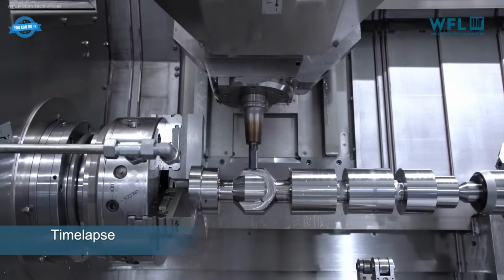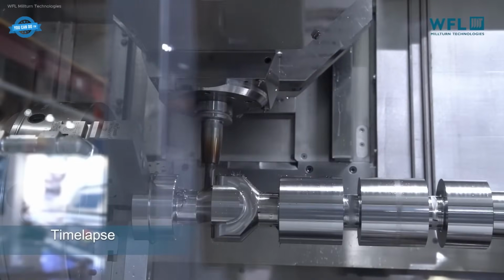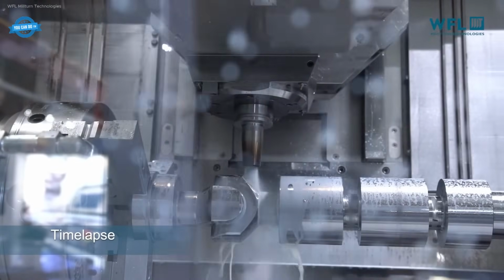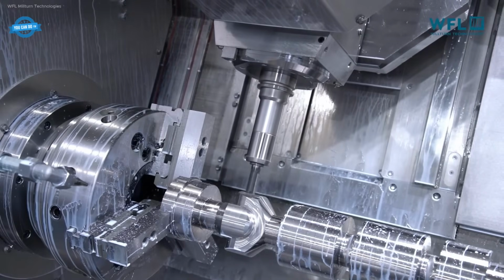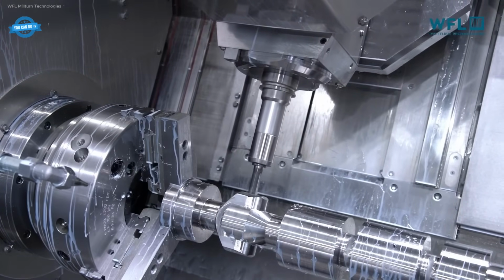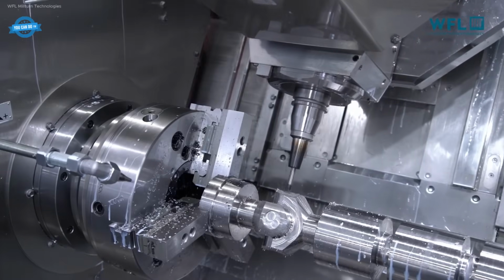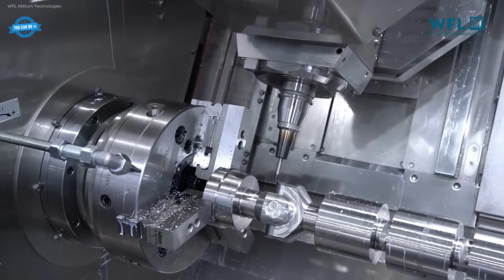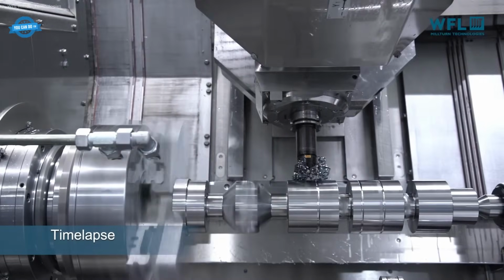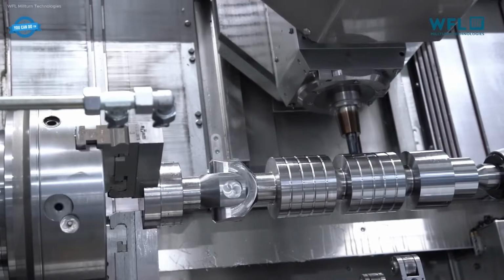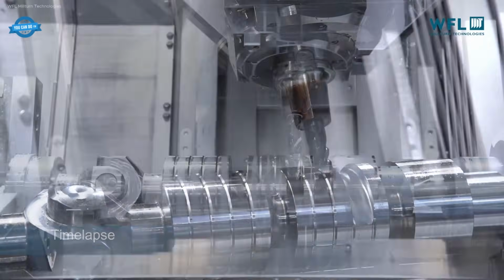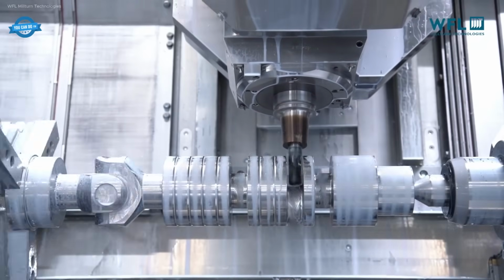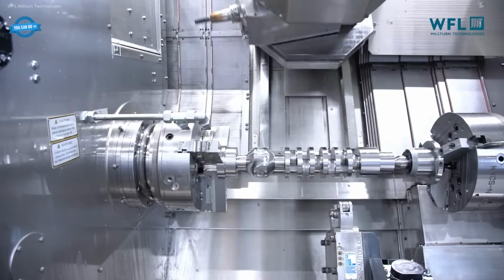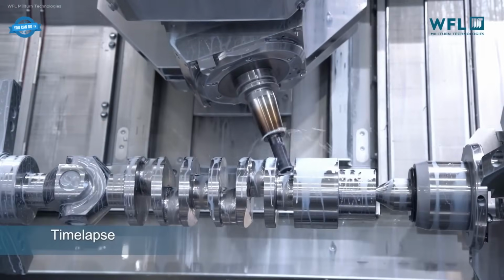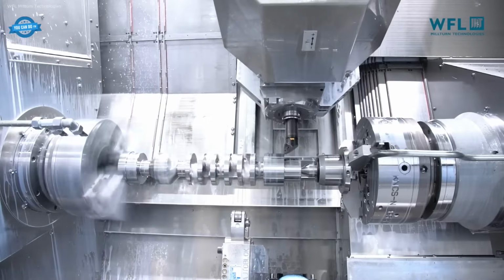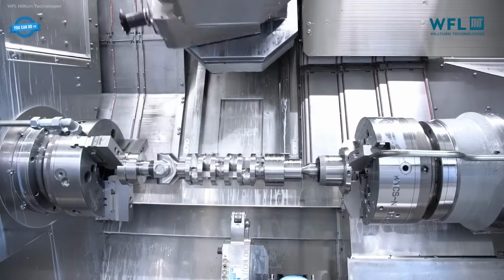Next, the B-axis milling spindle, capable of rotating plus or minus 110 degrees, performs complex 5-axis milling tasks. The spindle executes contour milling, drilling, and tapping from multiple angles. Deep hole drilling is also possible during this stage. The machine's Y-axis movement of 250 mm enables offset operations, while the X-axis travels up to 600 mm for detailed profiling. Depending on the machining requirements, gear cutting may be integrated into the process using specialized tools from the 40 or 80 position tool magazine. The SINUMERIK 840D control system coordinates all axis movements with high precision.